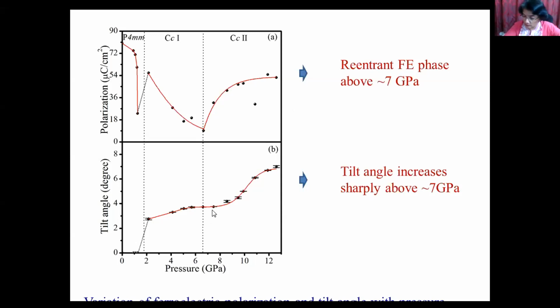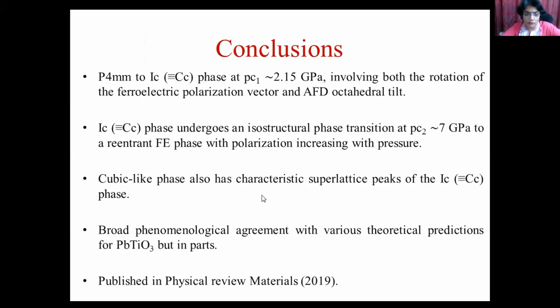And when we plot the tilt angle, we see that in this increasing ferroelectric phase, the tilt angle starts increasing very abruptly, which shows that this tilting is providing the required mechanism to accommodate the increasing volume and also to accommodate the increasing polarization. So this is the first experimental proof which